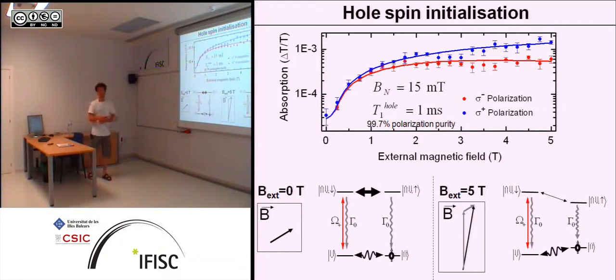But if you now apply a magnetic field in Z direction, which is parallel to the initialization direction of the electron spin, that means that the effect of the internal magnetic field, which is at 45 degrees, gets less and less important, and thereby the speed or the effectiveness of this coupling mechanism due to the electron spin precession gets less and less important, and you get less and less population from this state into that state, and that makes the system, once it's excited here, relax into that state by a vast majority, and only very seldomly in this state.